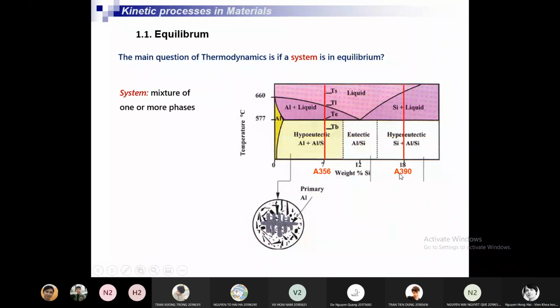So you have another chemical composition, for example, this alloy A390. This alloy possesses 18% of silicon, much more silicon than this one. This only 7, here we have 18. So for this alloy, the microstructure will be quite different from this one. Quite different, like this. So instead of primary aluminum, we have the primary silicon in this form, plus eutectic structure. Okay, so you can see the difference between the two alloys because of the different composition.